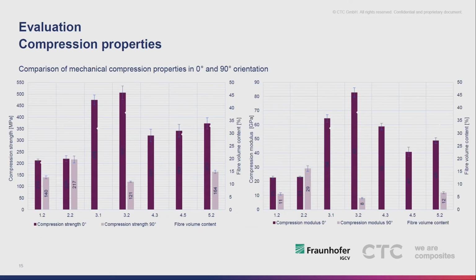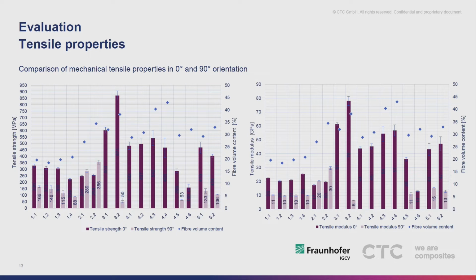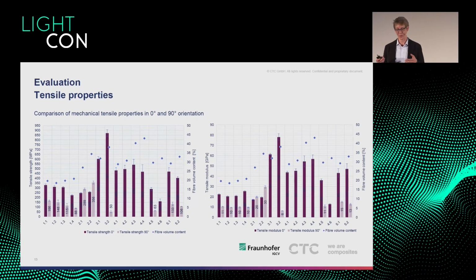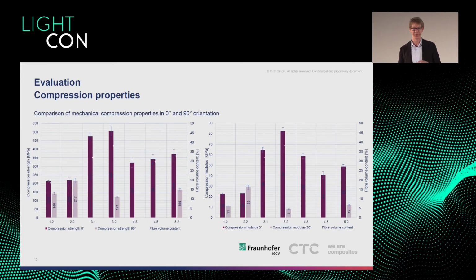Because maybe the practical difference between this very high 2.2 and the other ones is that one was embedded in polypropylene, the others were embedded in thermoset resins. And if you use a polypropylene, a thermoplastic material in general, as an adhesion material between the fibers, and you only use a very small amount because you want to integrate it into a thermoset, this means you have very little stretchy stuff between the fibers that you can pull on and do a high alignment. If you already have like 50% of the fibers being thermoplastic, it means you have a lot of wiggle room in terms of how much you can stretch, and the further you can stretch the raw material, the higher the alignment gets, the better the performance gets. So due to the fact that we need some kind of binder between the fibers and the stretching, we are looking at this kind of technology. We are mostly looking at thermoplastic applications if we actually want to do very, very high performance applications.